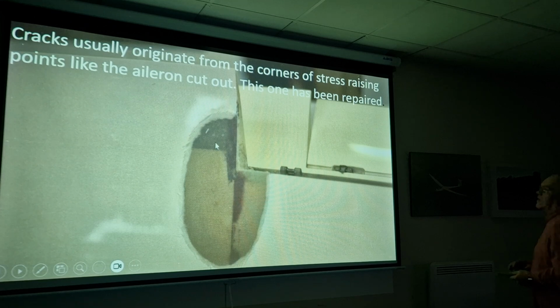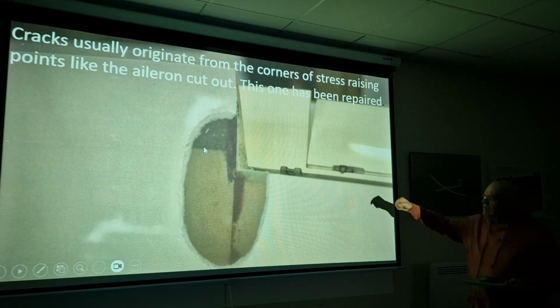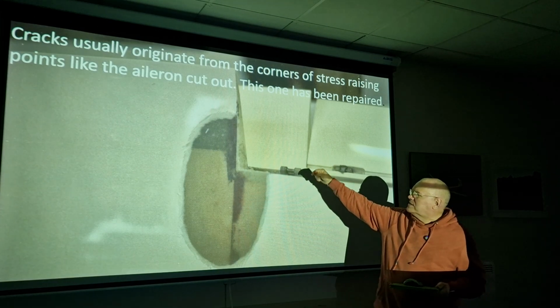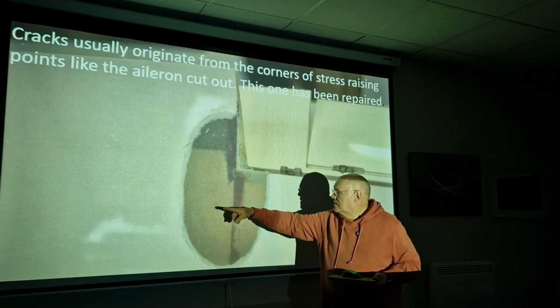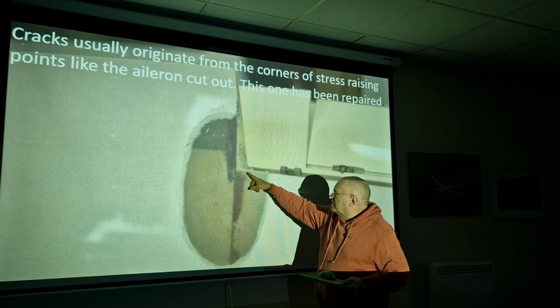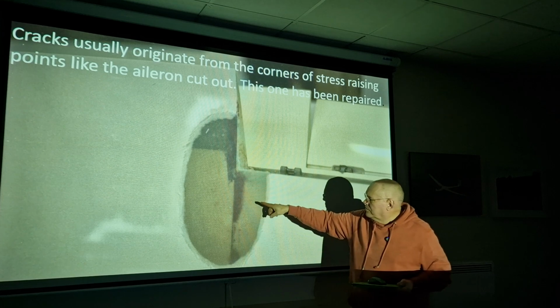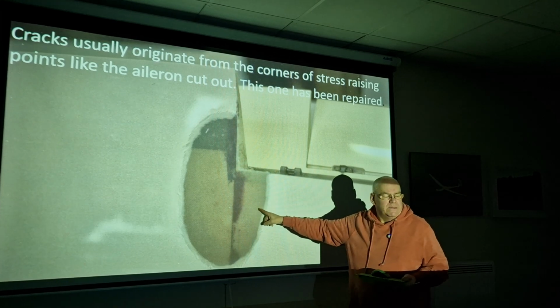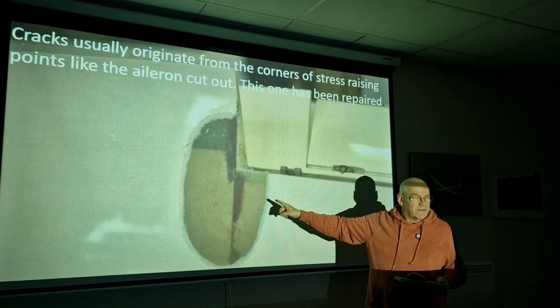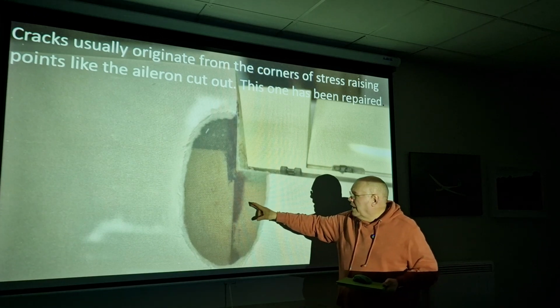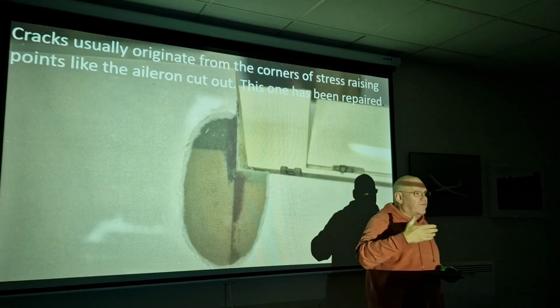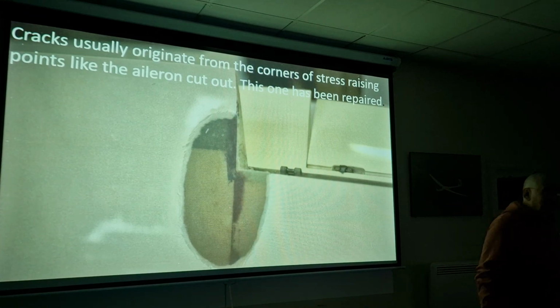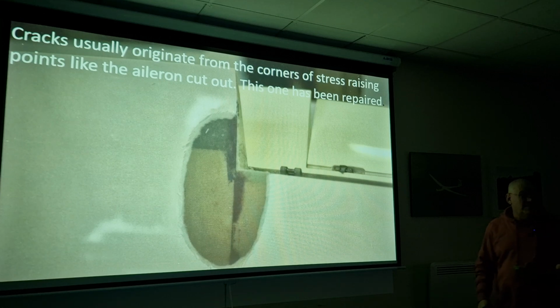Right. This is an SW19 aileron. Most cracks happen on the corners. There are only 3 layers of glass fibre here, so the glass fibre splice is only 1 millimetre thick. You think, how do you splice something to 30 to 1 if it's only 1 millimetre thick? It's actually quite easy. You just get a big block of 40 grit sandpaper and carry on. And when you're skilled enough, you can actually do it with grinders.